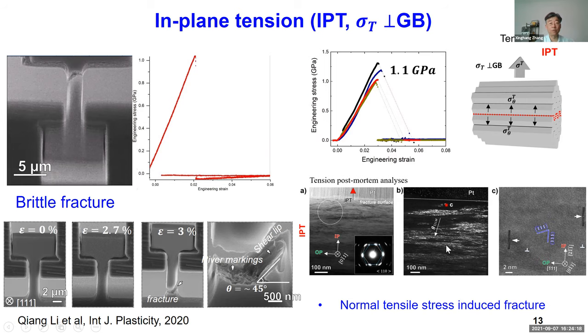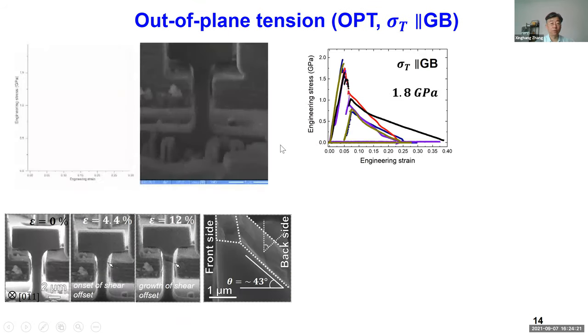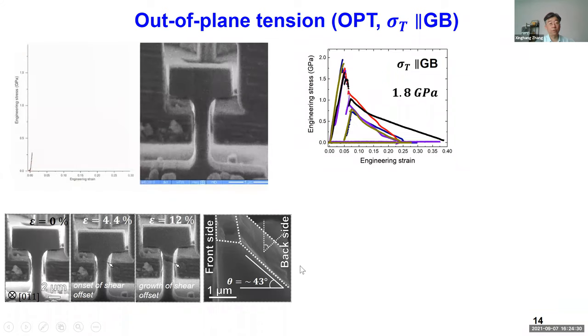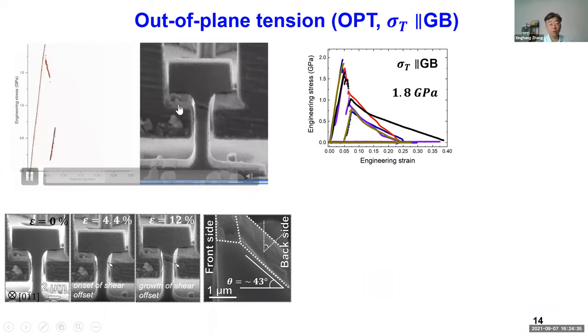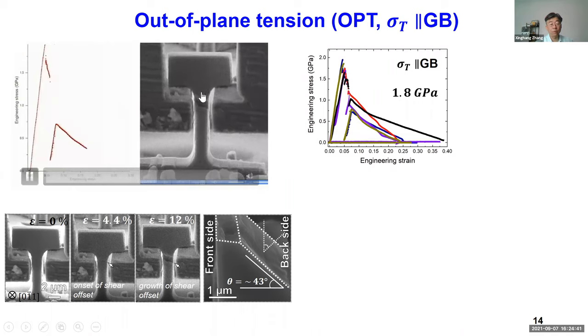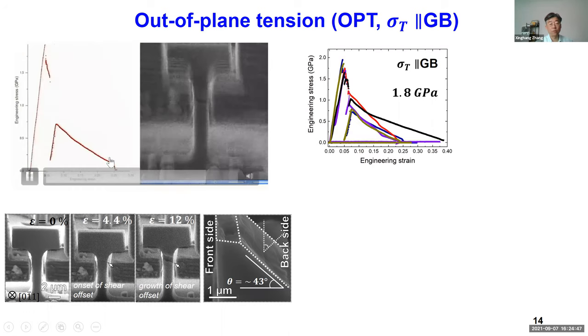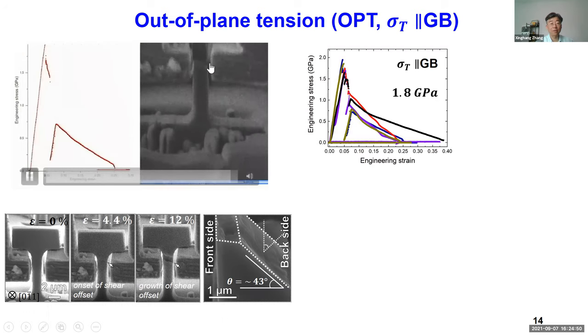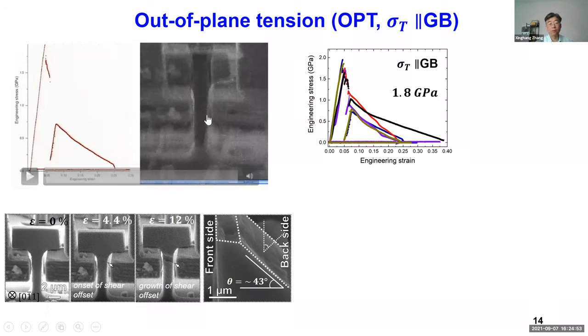The next experiment we did was out-of-plane tension. Same film, but pulling in the out-of-plane direction instead of in-plane tension. Same setup. And what you see here is quite different compared to the other one, because there is a load drop, but the whole sample didn't fail immediately. Instead, they failed one layer, and then the load can still come back up again, and then there's a gradual softening process. So this is better, it shows more plasticity compared to in-plane tension, but you do see some substantial load drops through multiple tests. And then it picks up again softly.